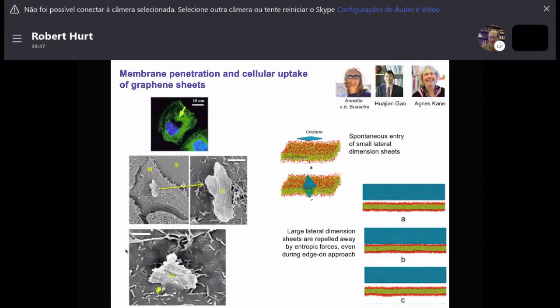And I have a modeling colleague, Professor Huajian Gao, who ran molecular dynamics simulations of this, and he would show that small graphene sheets can in fact spontaneously enter lipids this way. But if he looks at a large sheet, like the kind we're using experimentally, those sheets would not enter the lipid membrane easily. They would be repelled. It was difficult for a sheet of micron scale dimension to cut through a lipid bilayer.